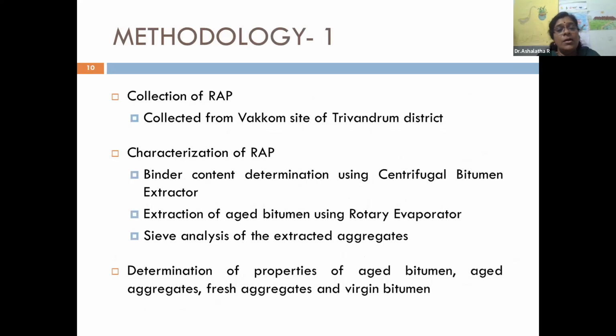And this was the methodology. So I already said it has two parts. In the first set, we were developing the procedure to be adopted. So for that, we collected RAP from two locations in Trivandrum city, and we characterized the RAP: the binder content determination using centrifugal bitumen extractor, extraction of the aged bitumen using rotary evaporator, and sieve analysis of the extracted aggregate was done.